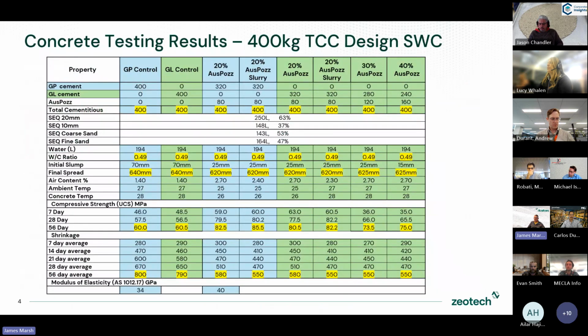This is probably what you're mainly interested in seeing. So what we have here is a typical design, super workable concrete, normally about 40 MPa. So it's 400 kilos of cement per cubic metre of concrete. What we've done is used a GP control and a GL control, which is the approximately 14% limestone cement control. Then we've done replacements with AusPozz at 20%. We've added 20% as a slurry because it forms a very nice slurry, about 70% solids. So that's another way to use it.